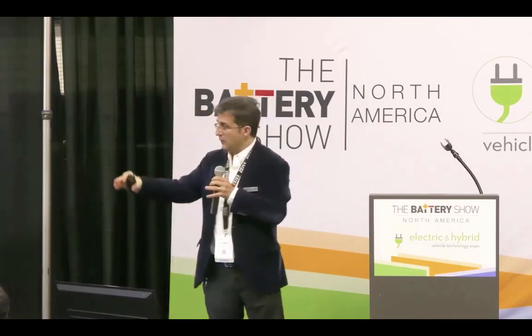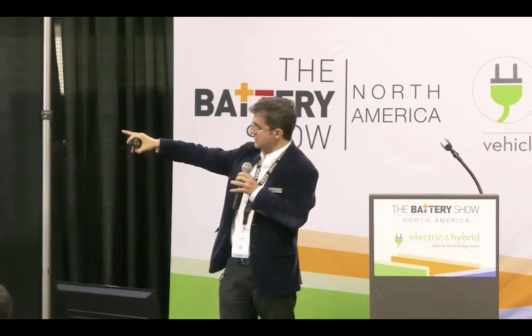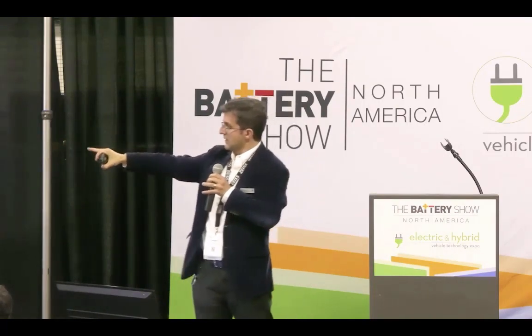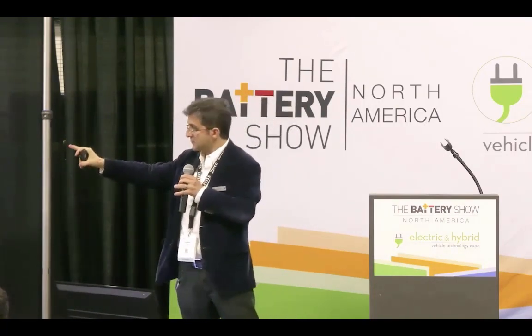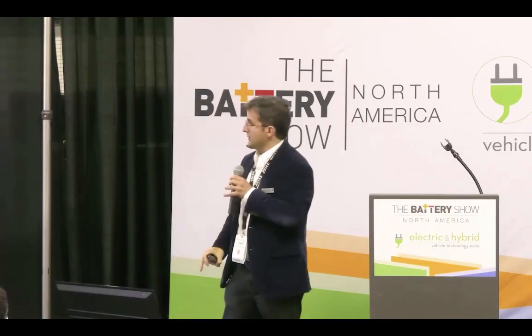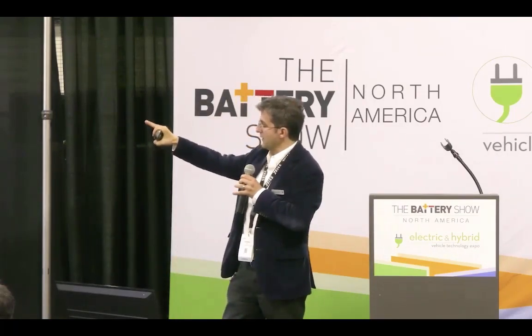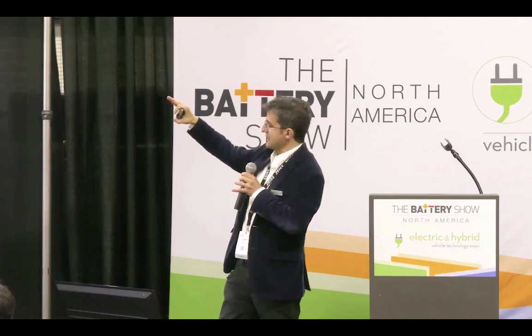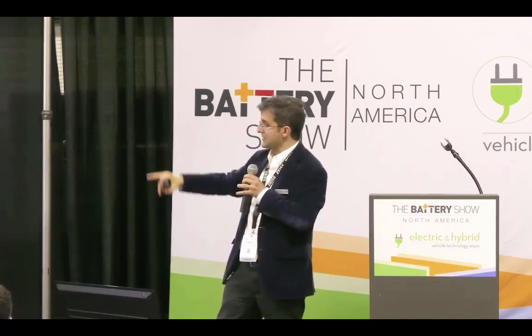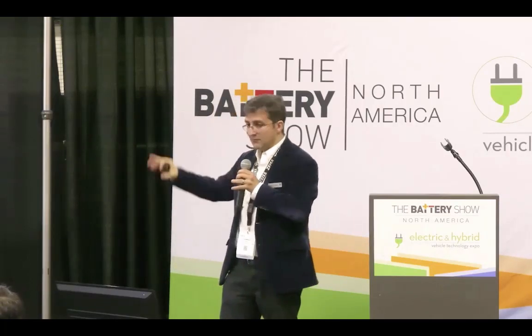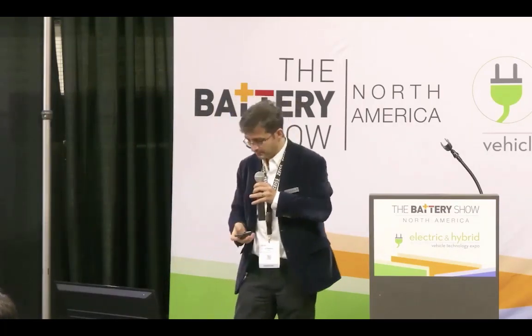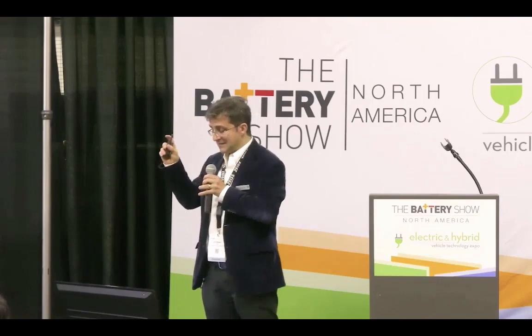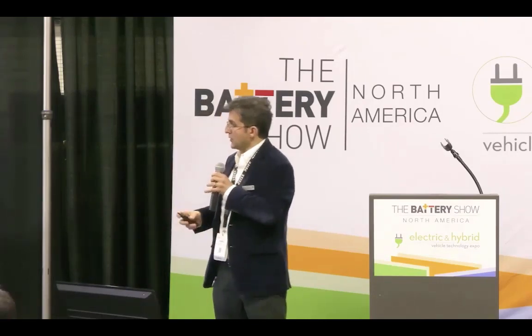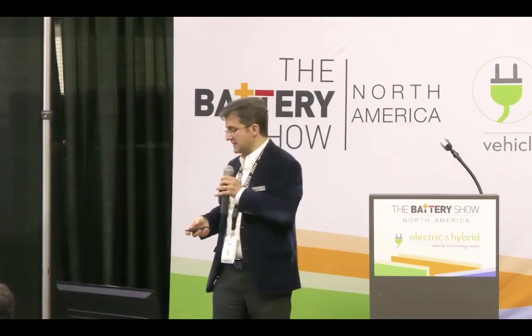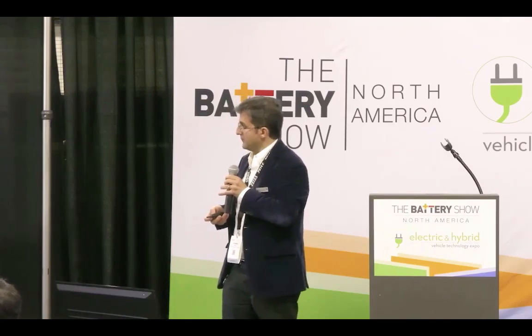And you can see now some of the quality assessments. You see the bright spots. Those are particle inclusions that are supposed not to be there. And on top of that, if you wait for a couple more seconds, you will see that we are able to detect a crack inside of the battery. And that's the segmentation of the cracks. So it is a very useful tool for doing non-destructive analysis assessments of batteries.